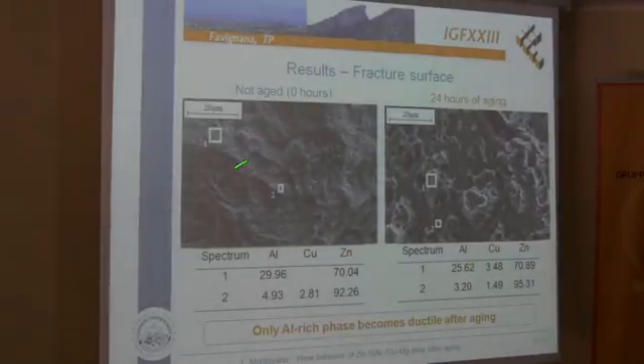As you can see, the fracture surface is mainly brittle. But after the aging, we observe that the aluminum-rich phase, indicated in both figures with spectrum 1, becomes more ductile, as the fracture shows the typical ductile surface with the presence of dimples. But only the aluminum-rich phase shows this modification, as the zinc-rich phase remains brittle.